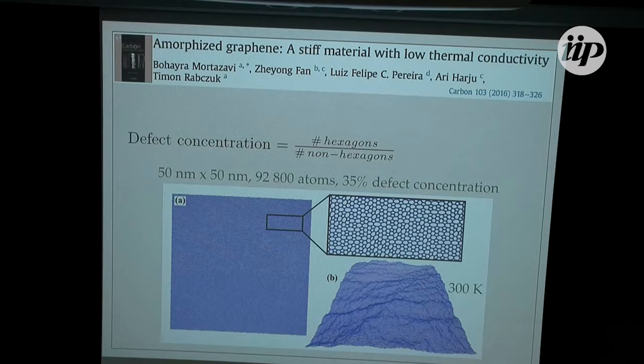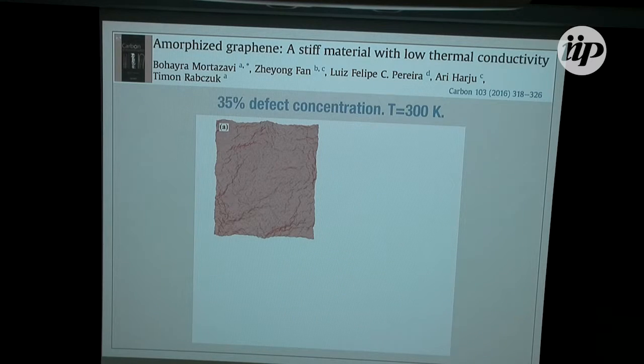We do this a whole bunch of times. We define a defect concentration as the ratio between hexagons and non-hexagons that are left over in the graphene patch. So here we get a 50 nanometer by 50 nanometer graphene patch, and we introduce a 35% defect concentration. Looking from up close, it looks like this, and then at 300K, it crumples. It gets a lot of these ripples, some of them because of these defects.